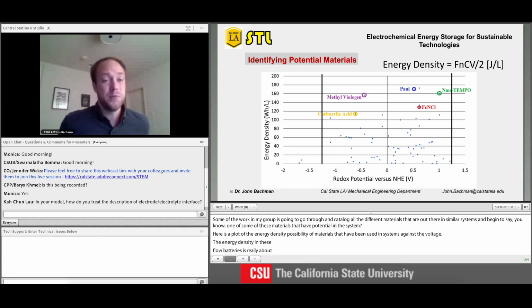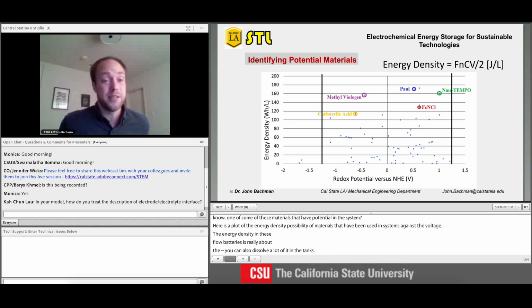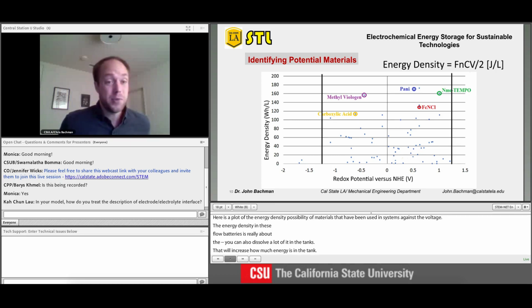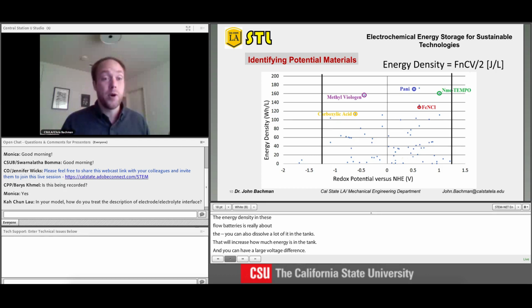But these highlighted black lines at the edge mean you can only pick materials with a certain voltage range, because as most people are aware, you can split water electrically if your voltage is large enough. So you're limited by this. You want the highest energy density possible, but you've got to stick in this window, otherwise you begin to create hydrogen and oxygen in your system, which is unwanted.